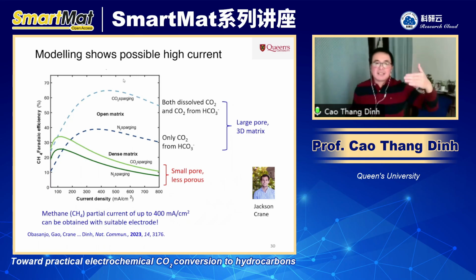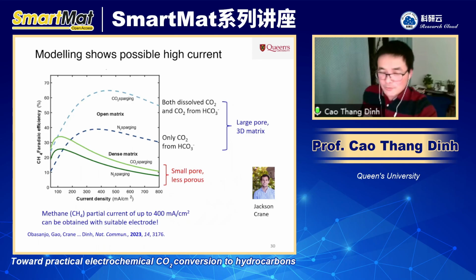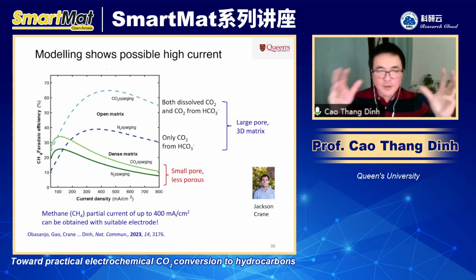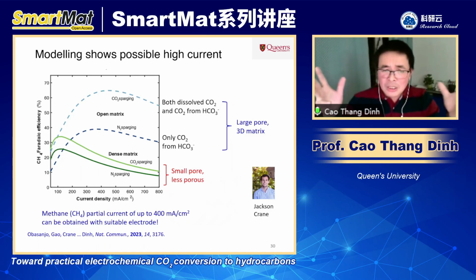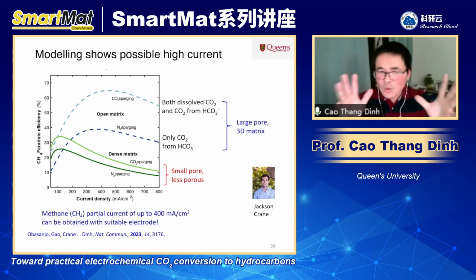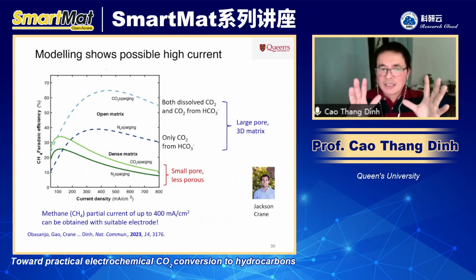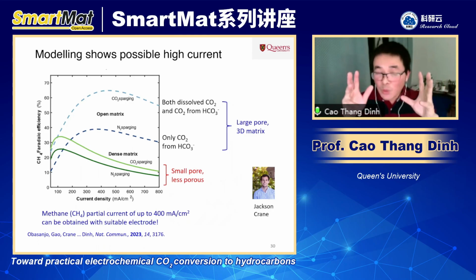So now we have the different scenarios here. The interesting thing is that if you can find something with the right porous structure and the right activity, you can achieve a methane selectivity of 60 to 70% at current densities over 400 to 500 milliamps per square centimeter, which is great. We are targeting a current of 200 milliamps and above, but now we can achieve even much larger current. So it all works out perfectly. Now the main task for us is to choose what the electrode would be.